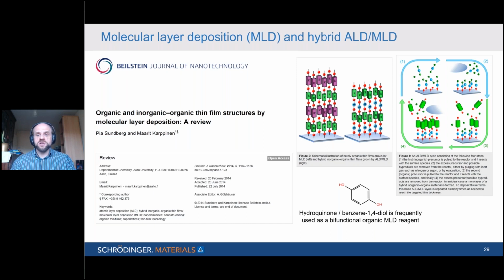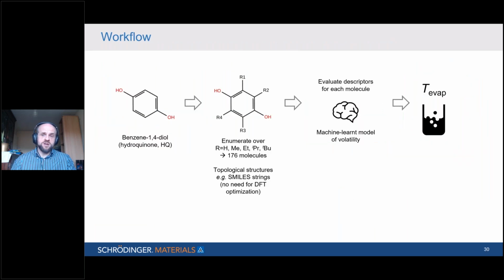So this is often used. Unfortunately, it's not very volatile, so we thought we'd look and see if we can improve on it. So this is our sort of strategy. We start with the base molecule, hydroquinone, and we look at modifications of it. We can change the R groups, change hydrogen to methyl or ethyl or isopropyl, for example. And this gives 176 different possible molecules.